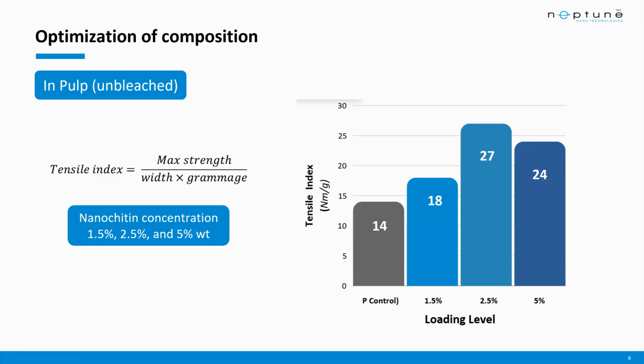Here, I want to make a small quick note that the local optimal that we're observing here is specific to the nature of the pulp, and in this case, it's an unbleached softwood pulp, and it needs to be adjusted for various different factors, such as bleached and unbleached, cellulose versus lignin content in the paper. But in general, you can get away with lower loading levels when the pulp is unbleached versus bleached. But as you can see over the next few slides, even in bleached paper pulp, the performance of nanochitin still works quite well.